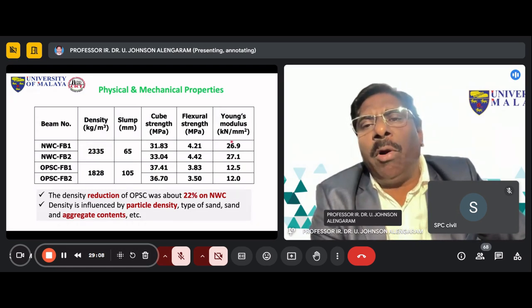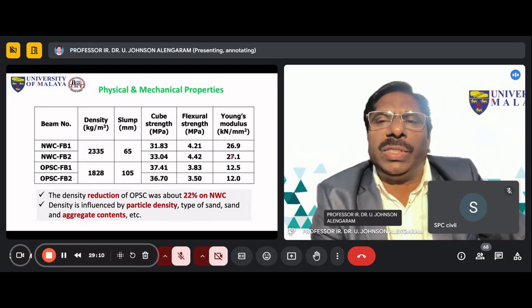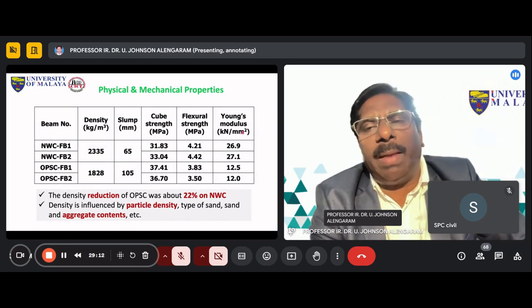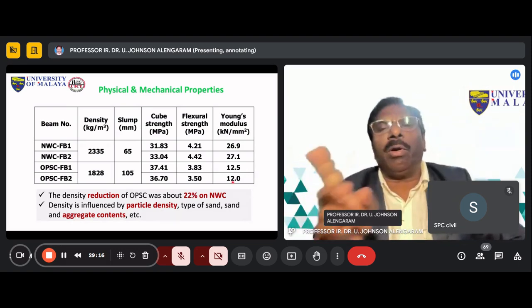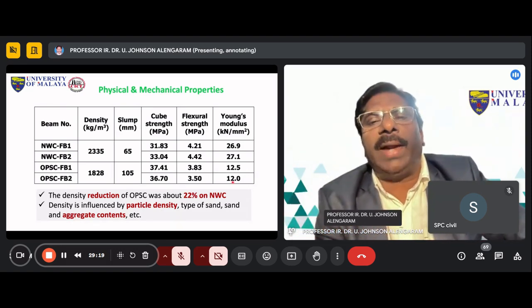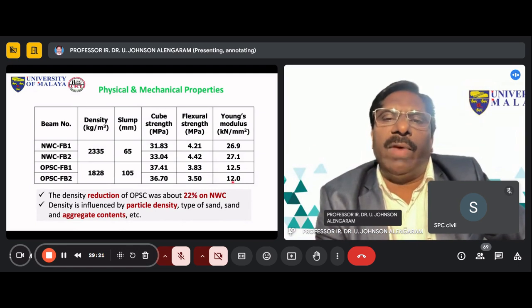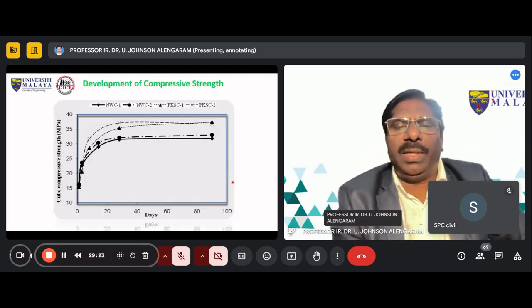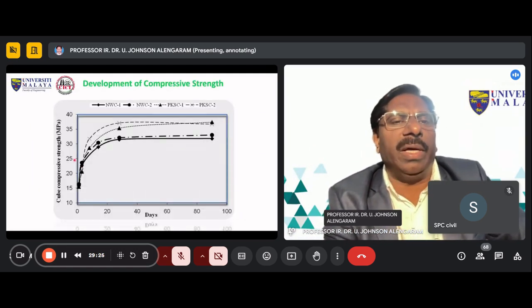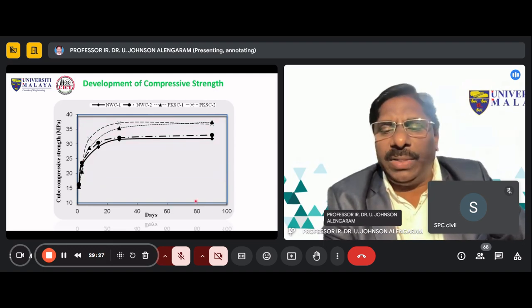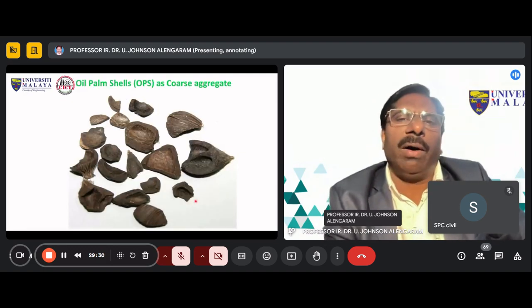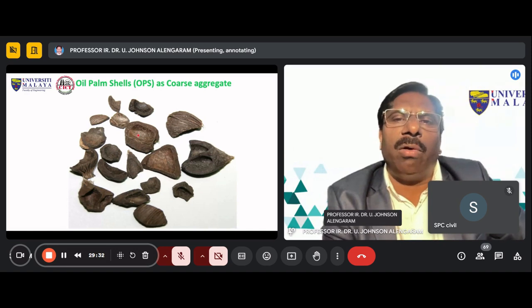But if you look into the modulus of elasticity, this is 26 gigapascal or kilonewton per mm square. This is only 12 gigapascal. When you have a lower modulus of elasticity, that means it will undergo more deformation. Whereas this one, if you look into this, this is the traditional graph for compressive strength versus days, which I have shown you. This consists of a convex and a concave surface, and the broken surface. Different surfaces have different characteristics.